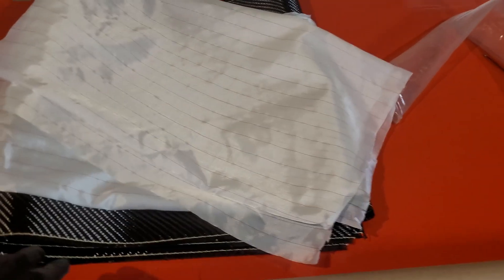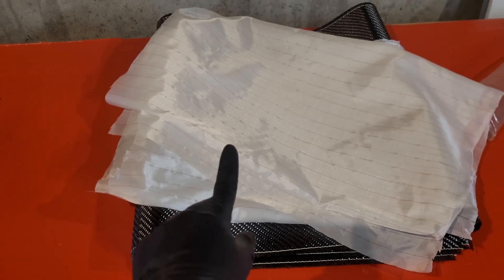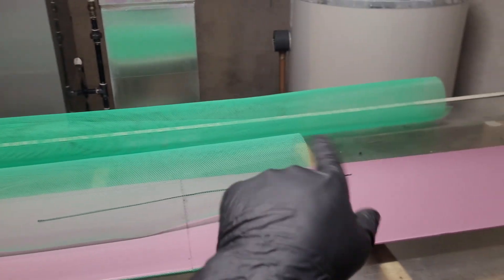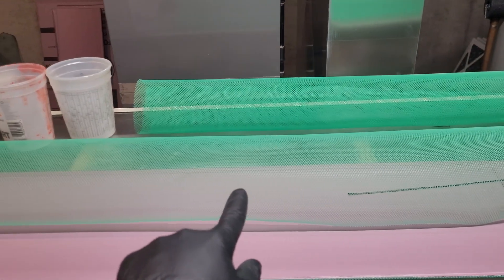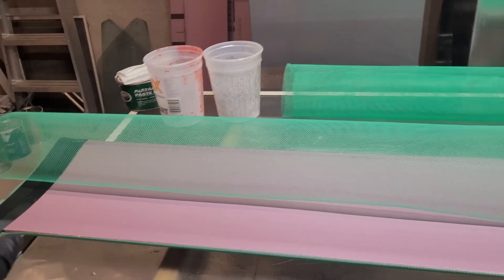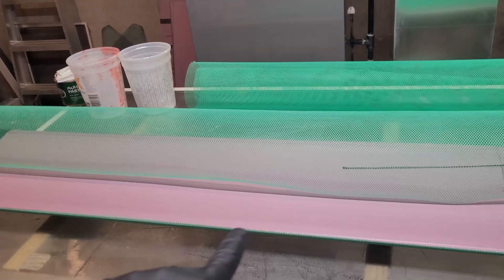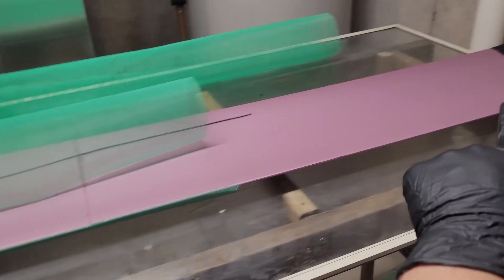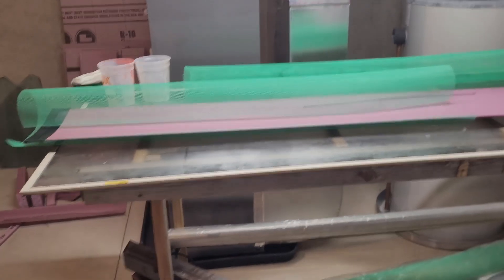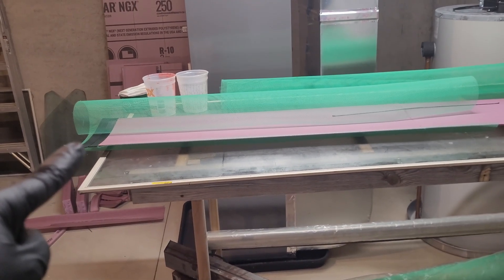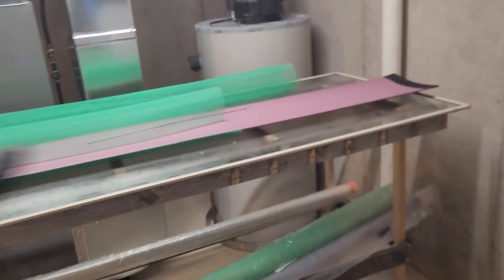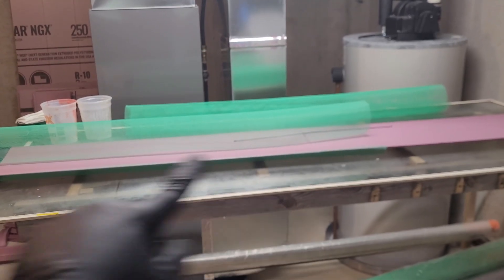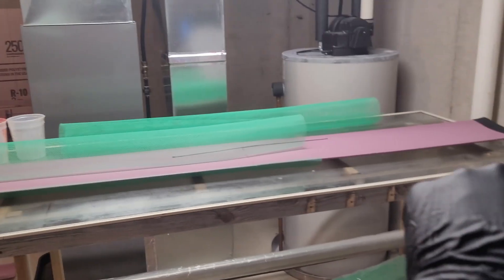Alright, so we have our two layers of carbon, our peel ply, and also our resin flow matrix green stuff. All this does is for resin infusion, this allows resin to travel back and forth more freely than just permeating through the fabric. And given the fact that this is such a big piece, I definitely want the flow matrix. I don't plan on having it feed in at one end and pull all the way across. I'm going to give it two feeds on either end. So two cups of resin and then have it pull right in the center so it just pulls from either side.